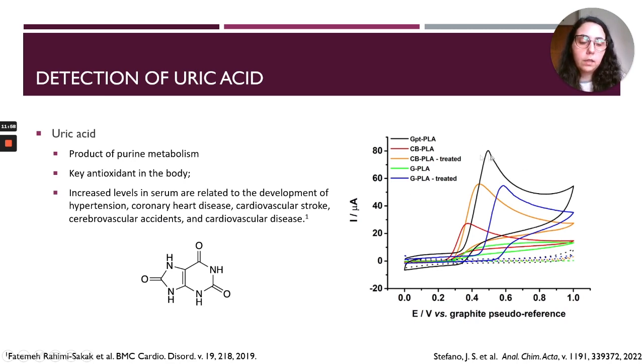So right here, on the right side, you can see the oxidation of uric acid using the developed filament and the commercial filaments, treated and untreated. We can see that the untreated filaments have very poor performance. The treated commercial filaments have a better performance, but the filament developed by us here in black has shown superior performance even without any pretreatment.